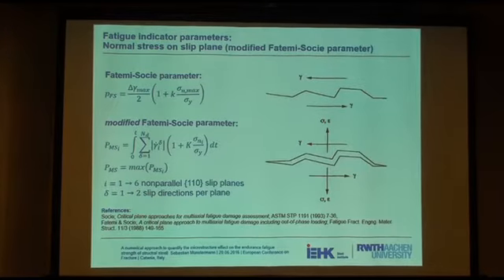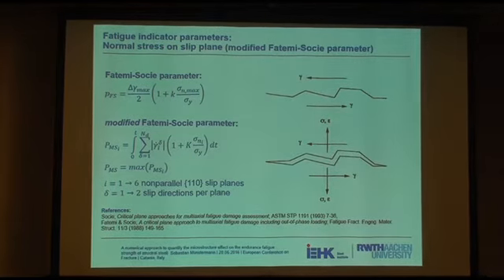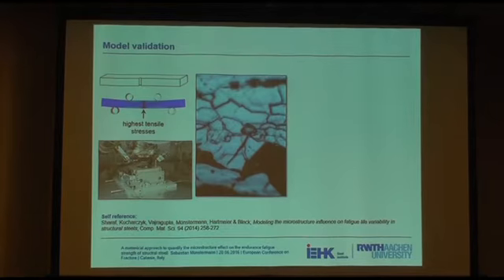Of course, there are also other fatigue indicator parameters, a very famous one by Fatemi and Socie. And in fact, we tried to combine them and resolve them on the individual slip systems. So here you see that both the normal stresses on the slip system and also the accumulation of plastic slip were considered in this.